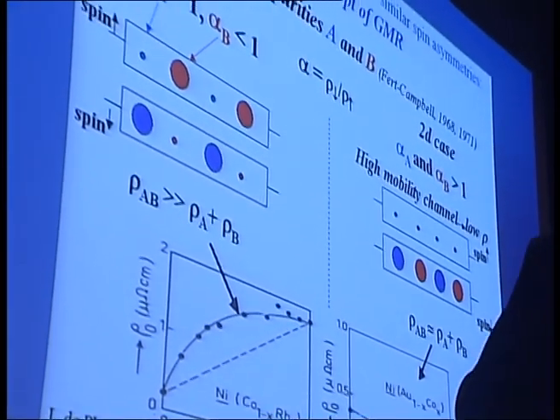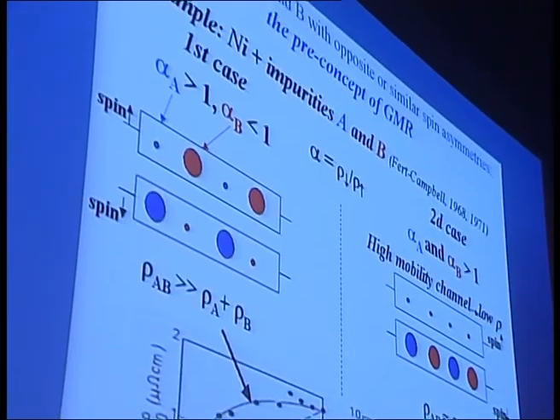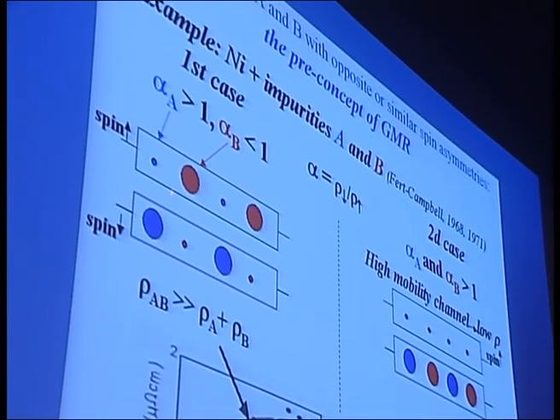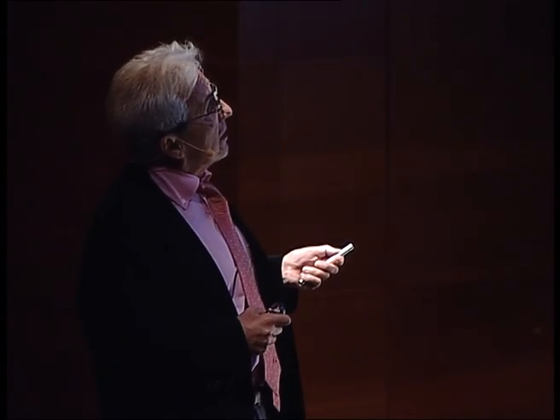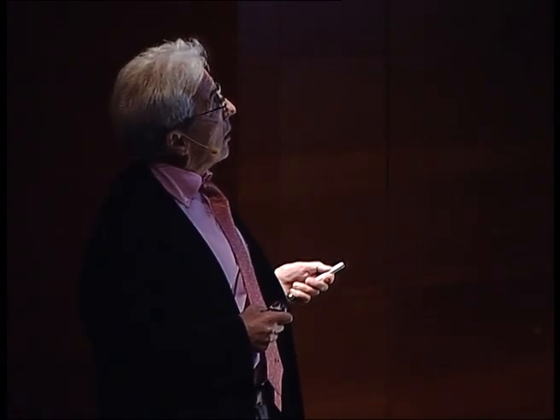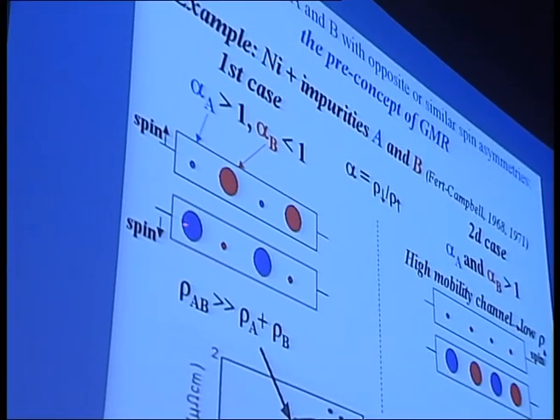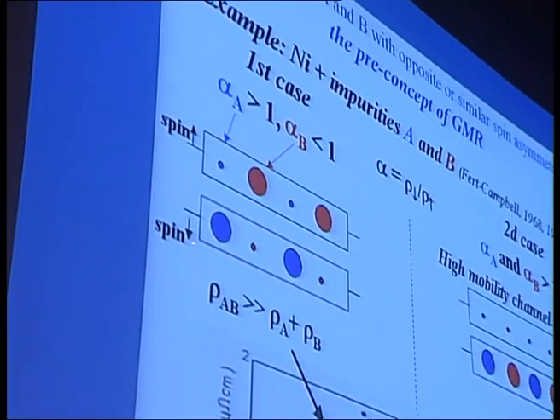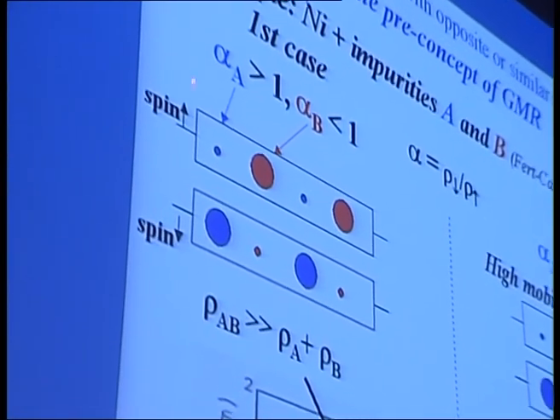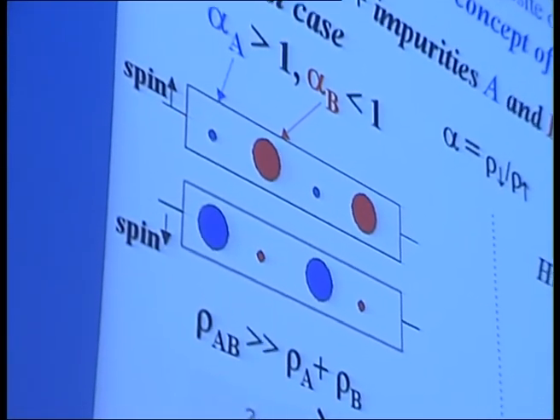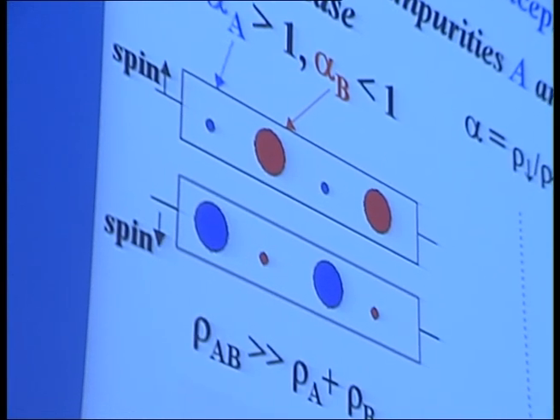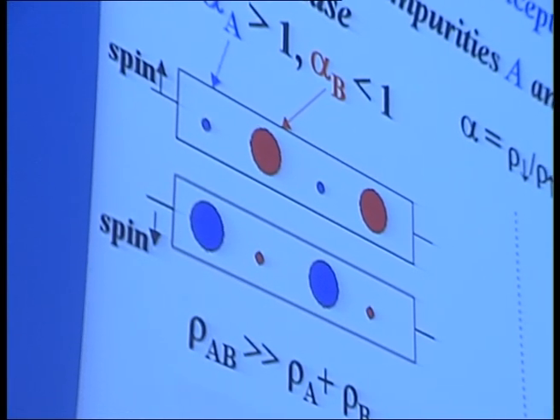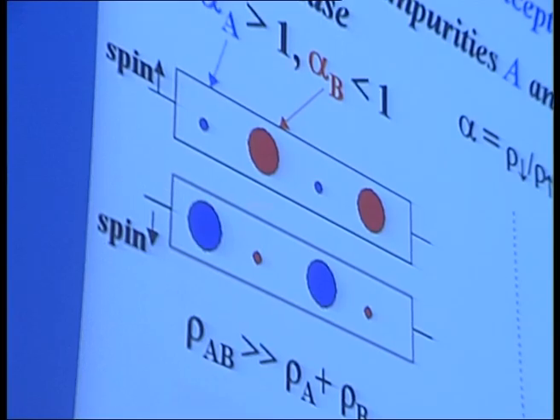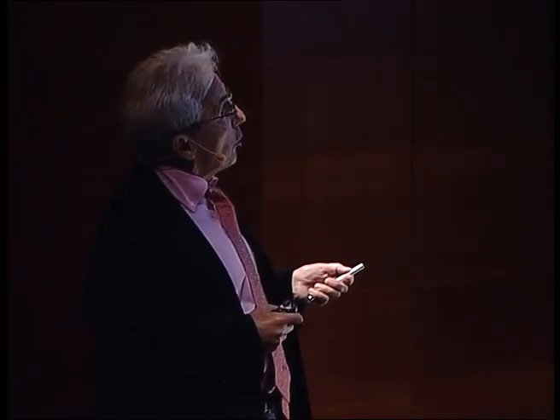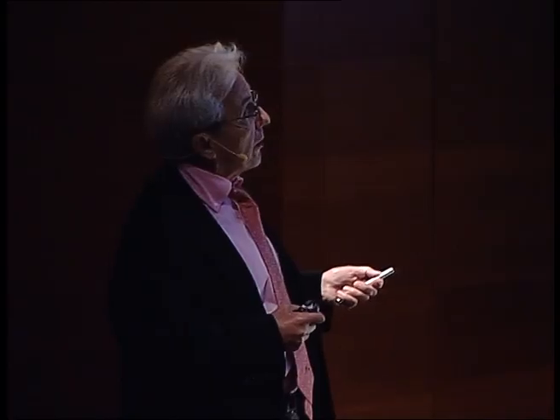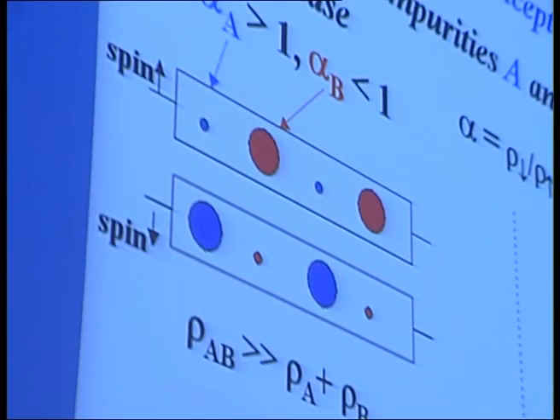Suppose that you dope nickel with two types of impurity, A and B, and first suppose that they have opposite spin asymmetry. That is, the impurity A will introduce a strong obstacle in the spin down and will leave more or less free the spin-up channel. And the opposite for B. If you put at the same time in the same alloy A and B, of course, there will be strong scattering. The electron will be slowed down in both channels, and the resistivity will be strongly enhanced.